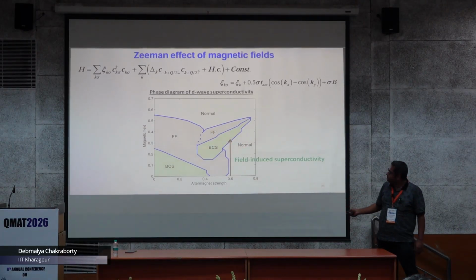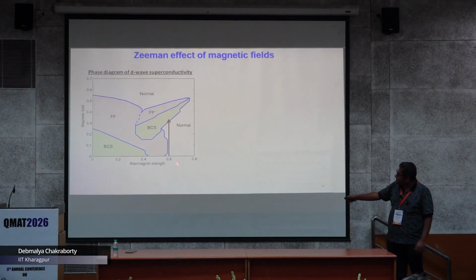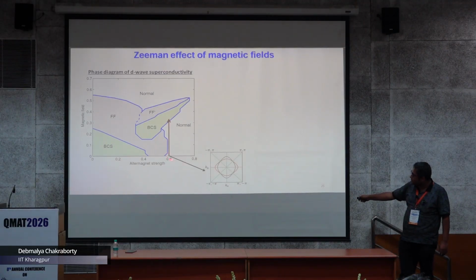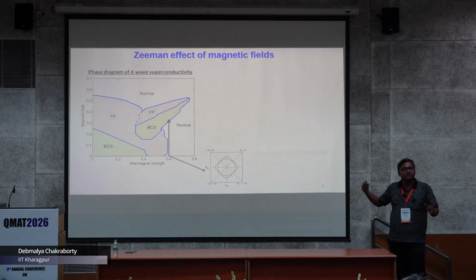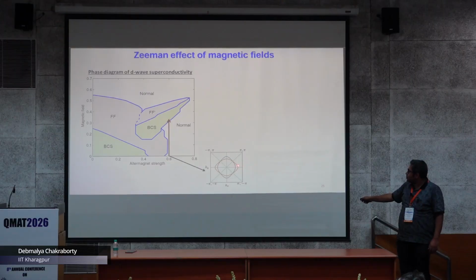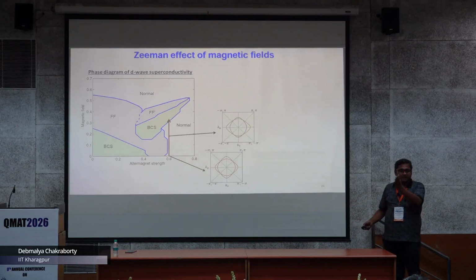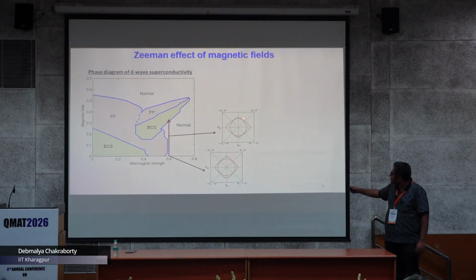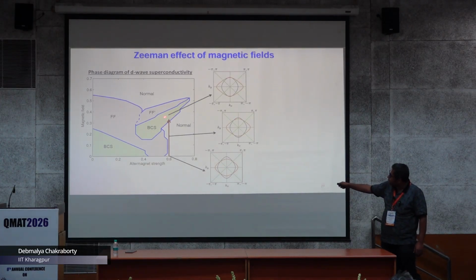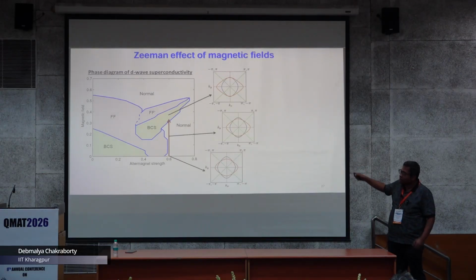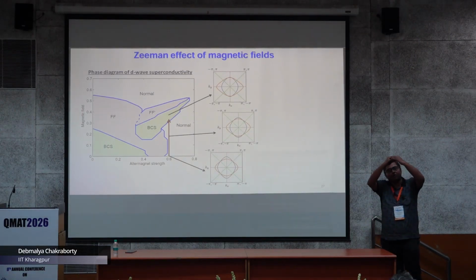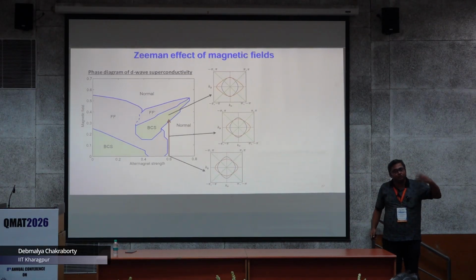Why is this happening? So if you look at the Fermi surface at this point, let's say at this point, this was the spin split Fermi surface that I showed you earlier. So these were the nodes, these are the maximum spin splitting. Now if you keep on increasing the magnetic field, Zeeman field, these nodes actually go closer to this point, kx equal to 0 point. If you keep on increasing near this region, what happens, the nodes, they coincide and they go to the antinodal region of the superconductor.